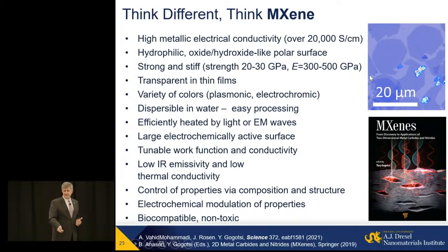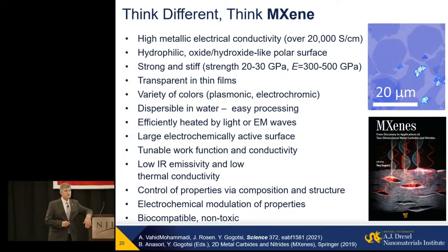Those flakes are single layer flakes of titanium carbide, Ti3C2 in this case, sitting on a silicon wafer. This is actually an optical micrograph. I've never seen single layer flakes of dichalcogenides or oxides of that size. And the reason is very simple. They will break from just a vibration in liquid. What does it mean? MXene is very strong. It's strong and stiff. Only ideal crystals of single layer graphene or boron nitride will be stronger. It's stronger than any other solution processed material.